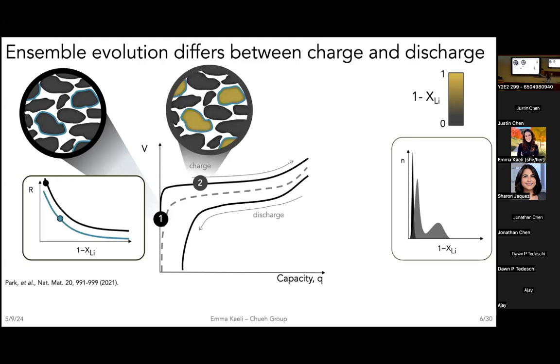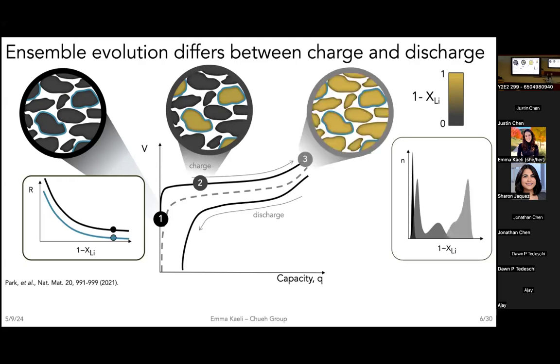And because the resistance decreases as a function of lithiation state, they continue to get better and better. They continue to have lower and lower resistance, and you start to get a divergence of lithiation state as you charge. Now, eventually, the high driving force in moving away from the redox voltage of those uncharged particles is going to make your system approach more of a unimodal behavior in terms of population distribution among lithiation states, and you can get more unimodal behavior towards top of charge.